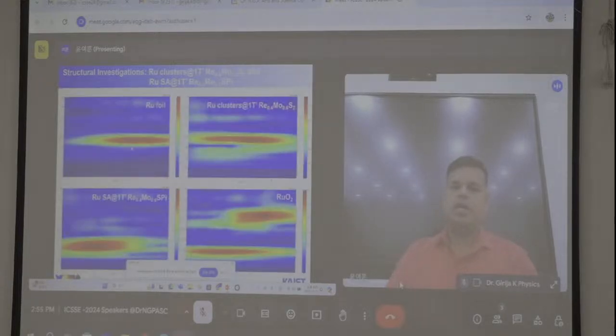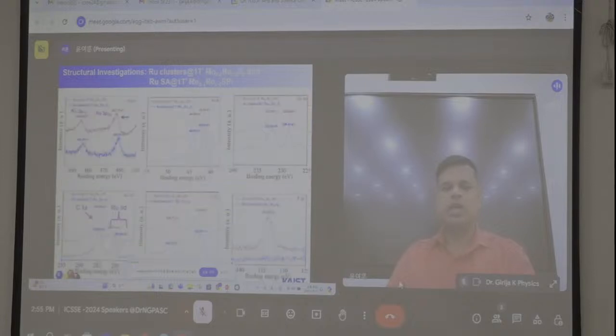So I also do the EXAFS analysis to compare with the foil and our commercial catalyst, because this is below 2. You can see this is after 2 because of the R value, and a similar observation I observed for the ruthenium oxides and the cluster also. And when I compare the cluster and our single atom catalyst, you can see a higher potential shift for the binding energy for ruthenium 3p and ruthenium 3d. Usually this is for carbon peaks, but 3d is close to the carbon. But for other sources like the substrate material, there is not much shift after modification, before or after single atom transformation. From the studies we can claim that the ruthenium is not doped. Thus ruthenium on the substrate is like a single atom modified with the substrate.